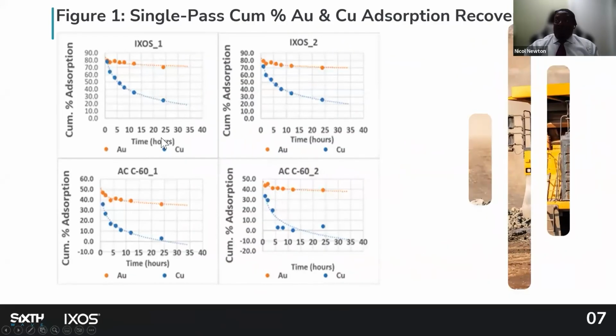Now, when we leached the solution, we collected enough solution to run 2 adsorption tests. In fact, 4 adsorption tests, 2 for the IXOS beads, and then 2 for the activated carbon. With the IXOS beads, we ended up with improved recoveries for the gold, or selective recovery for the gold compared to the copper, but still we picked some copper. With activated carbon, there wasn't very good recovery, and there was virtually no copper recovered.